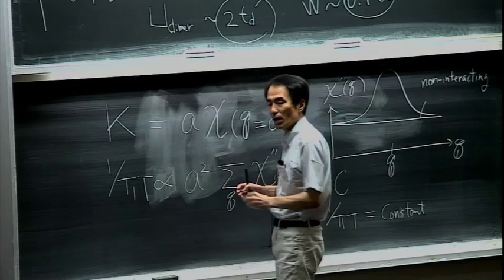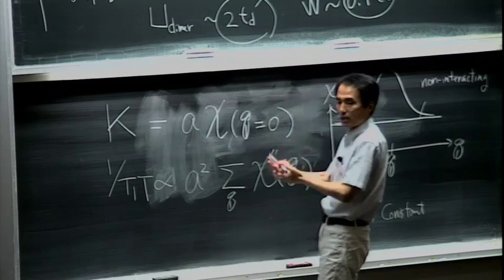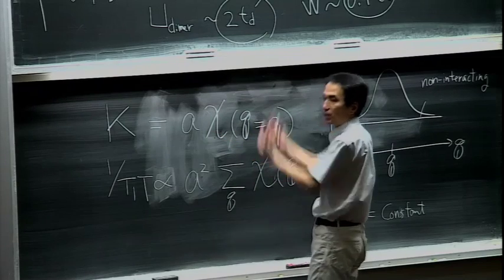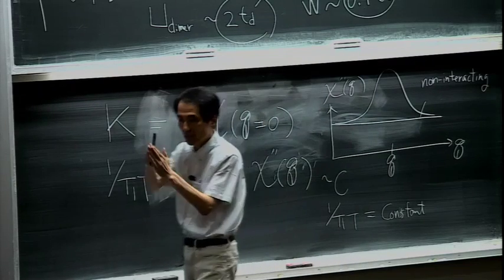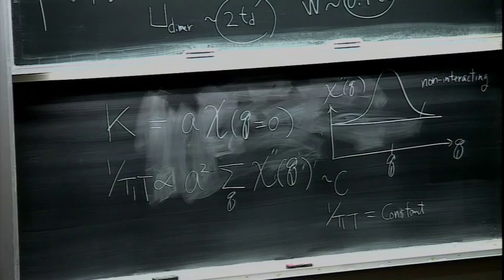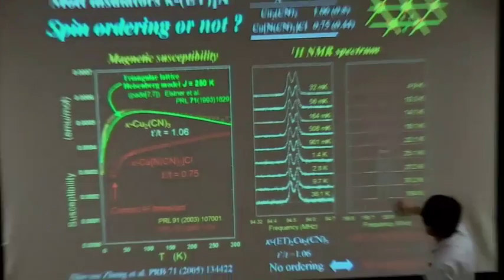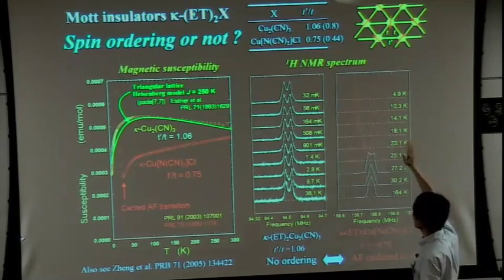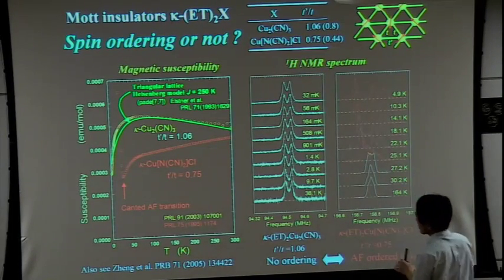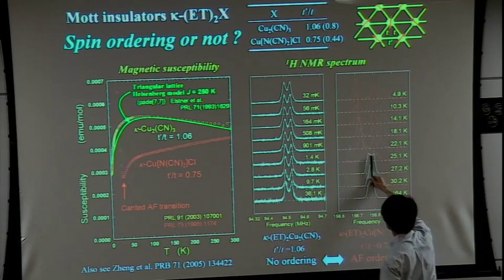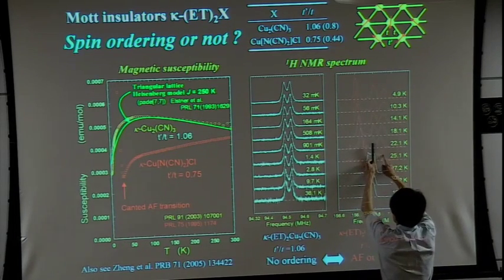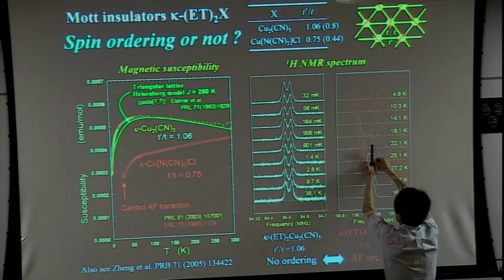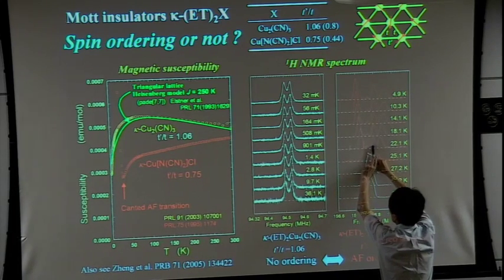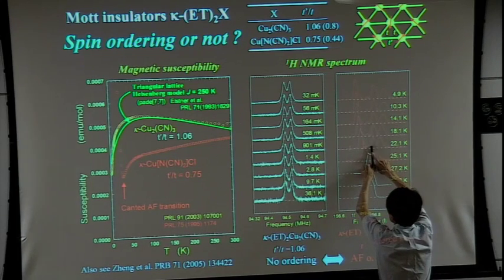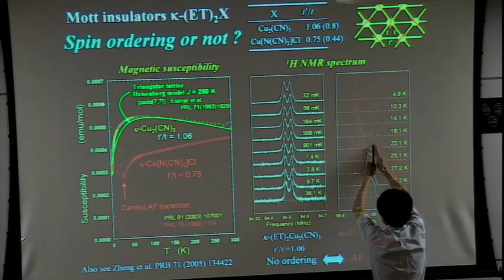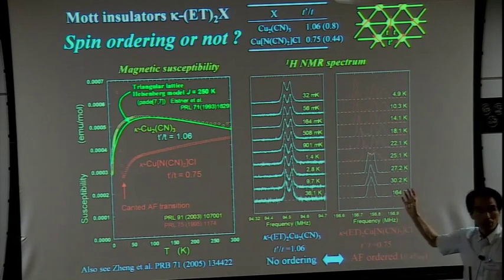It's very small. However, once the spins are ordered, the magnetization becomes very huge, so this shift is resolved. This is clear indication of magnetic ordering. Below 27 Kelvin, line splitting occurs. This means that under the applied field, some nuclear spins feel an additional positive field, some other nuclear spins feel an additional negative field, and some spins feel a very small positive field. Anyway, this is the generation of an internal field.